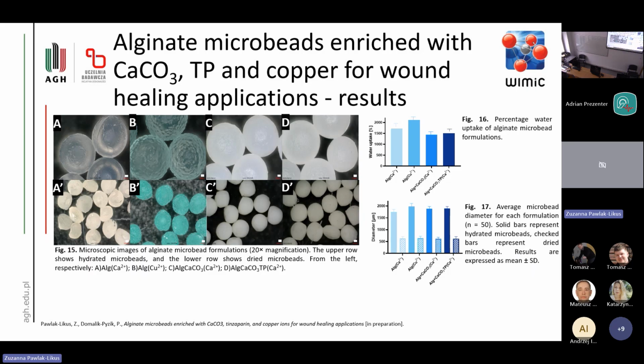So microscopic analysis showed uniform microbead morphology. And as we can see, from the left, it's pure alginate with calcium, then alginate cross-linked with copper, alginate with calcium carbonate, and alginate with calcium carbonate and tinzaparin. And as we can see, the microbeads that were cross-linked with copper had the roughest surface, and also they had the highest water uptake and the biggest diameter, both before drying and after drying.